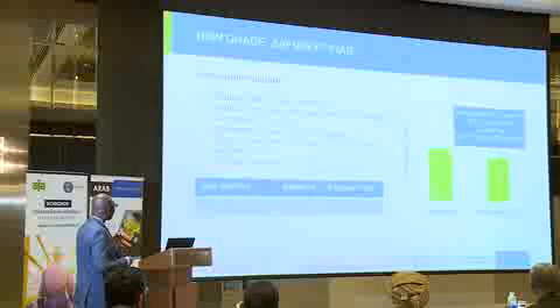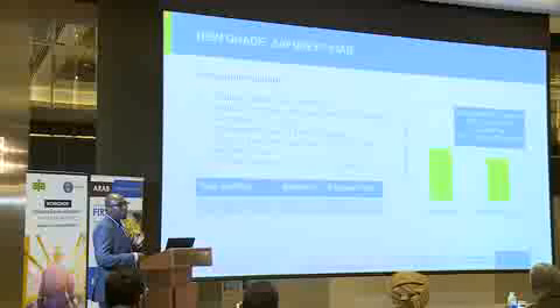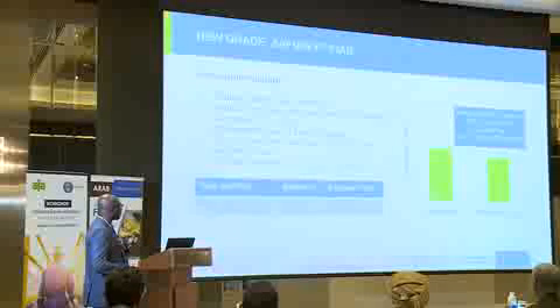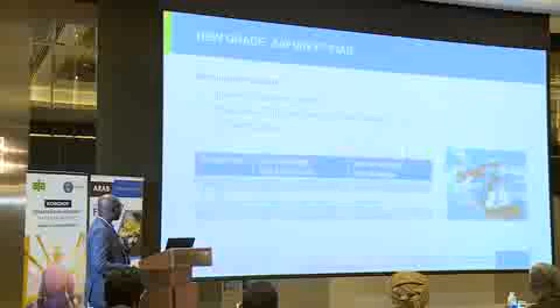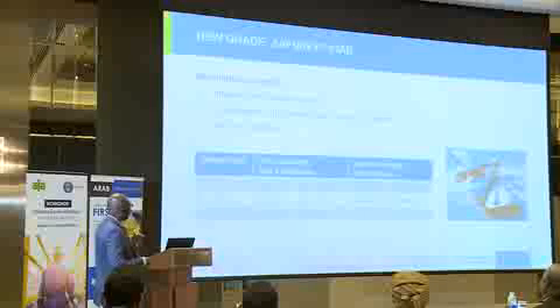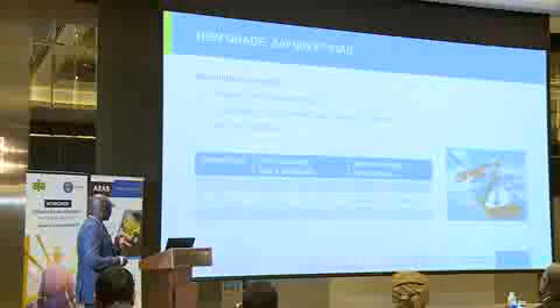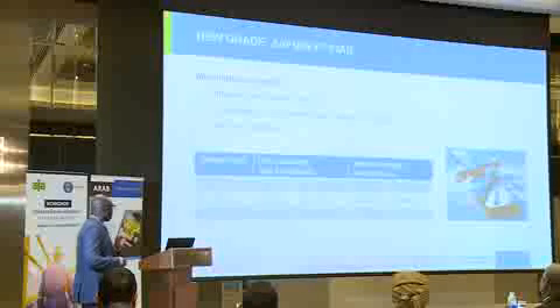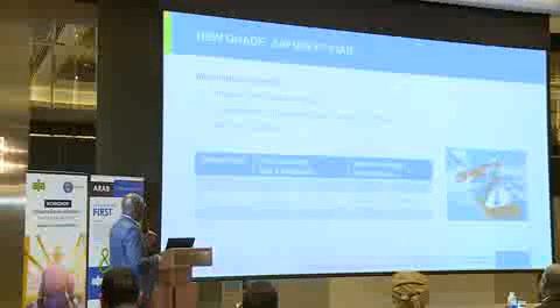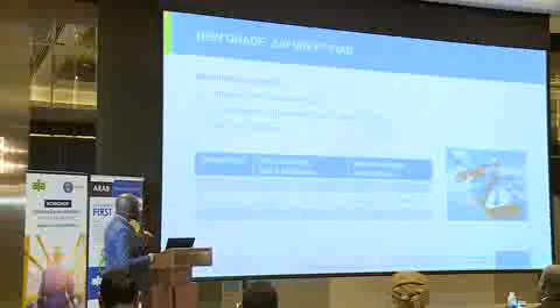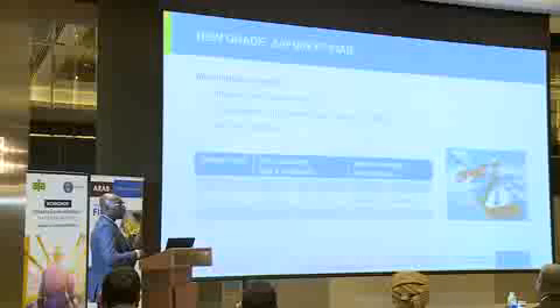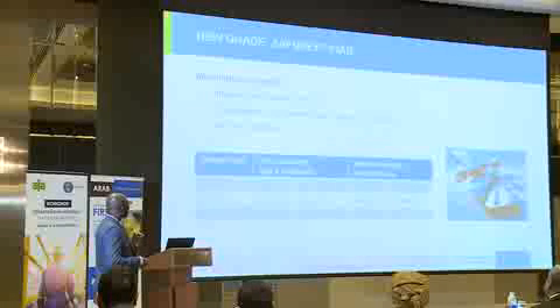These are some of the standard tests that are carried out on Safurex, although, let's say, pitting is not an issue that we deal with in urea plants. This table shows the improvements in mechanical strength, both at room temperature and at elevated temperature of 250 degrees. The ductility of the material is also improved despite the high strength.